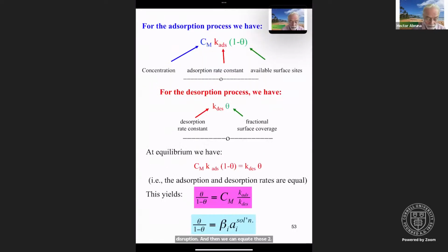For the rate of adsorption, we have the concentration of M in solution. We have the rate constant, K adsorption, and the number of available sites, 1 minus theta, right? Meaning, what's my concentration in solution, how fast it can do it, and how many sites I have that I can get into. For the desorption process, we have surface coverage, what fraction is covered, and the desorption rate constant. And so at equilibrium, these two processes have to be equal and opposite. So you can equate this and that. So we have C_M K adsorption (1 minus theta), as we had here, equals K desorption theta.